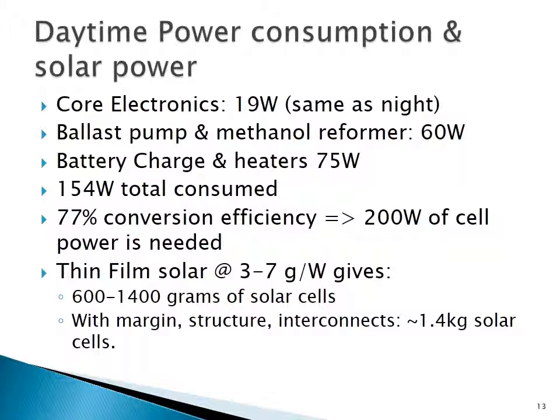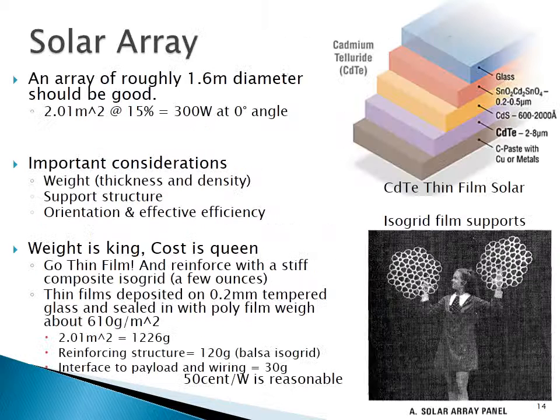So daytime power consumption, you still have the 19 watts from nighttime, plus in my system you have a ballast pump that takes the hydrogen out of the balloon and into a tank, and a methanol reformer, which isn't going to take that much energy. But I just budgeted 60 watts for that system, and battery charge and heaters 75 watts during the day, so 154 watts consumed. At 77% conversion efficiency, you need about 200 watts of solar cell, and I think thin films are the good choice for that.